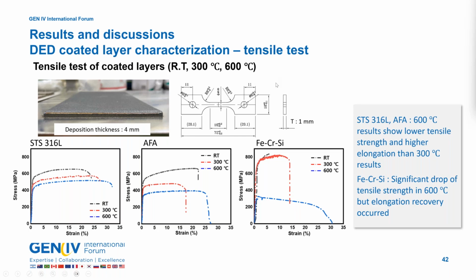For STS316L and AFA, the result at 600 degrees C showed lower tensile strength and higher elongation compared to the result at 300 degrees C. For iron chrome silicon, there was a significant drop in tensile strength at 600 degrees C, but elongation recovery was observed.